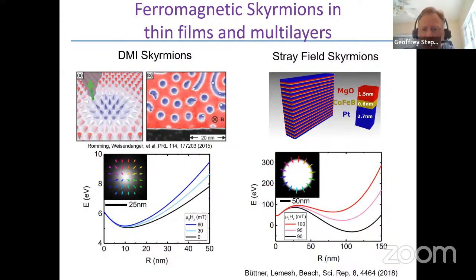Whereas in a multilayer stack, the DMI is responsible for controlling the chirality of a skyrmion to make it Néel and so forth. But the energetic stability of that skyrmion and the ease with which it can be created and stabilized is really due to the stray fields. So the energetics is that of a magnetic bubble, but with the DMI, that magnetic bubble has a chirality that allows it to be manipulated in a controllable way and so forth in these kinds of structures.